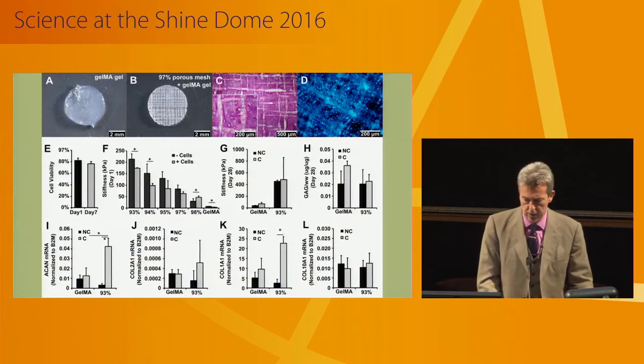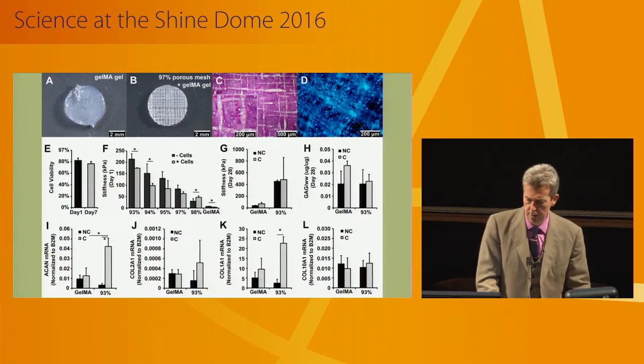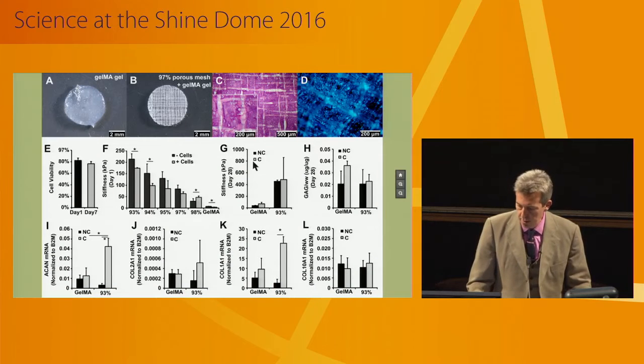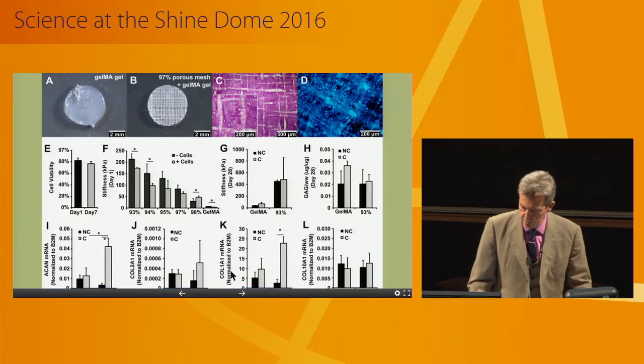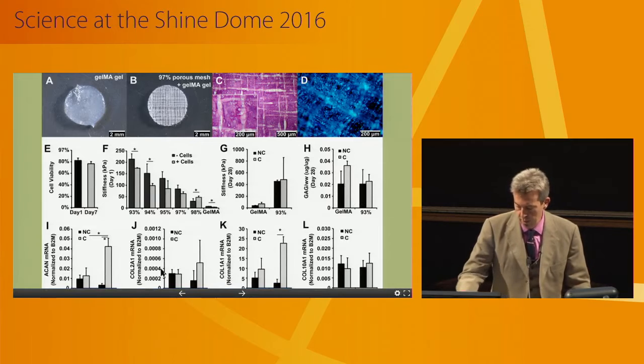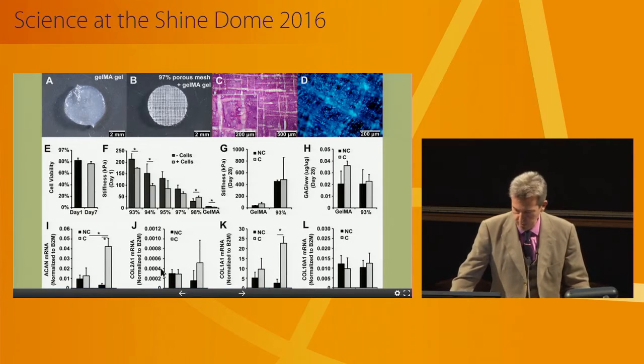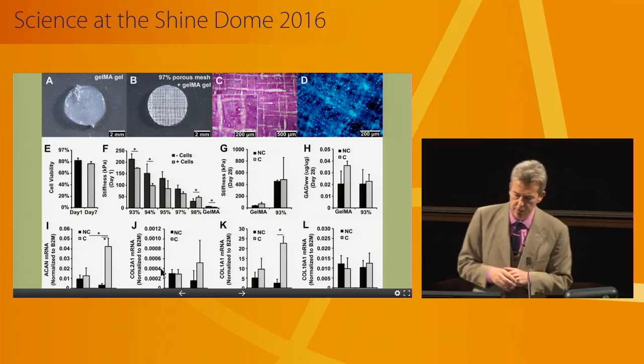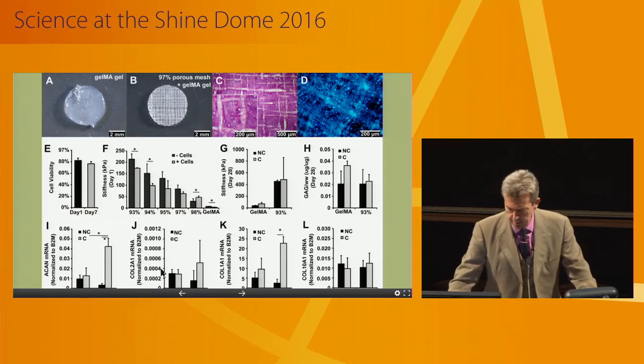But what about the biology? Here you see a long-term culture with human chondrocytes, which are the cells which you will find in the articular cartilage. And you see here that the cells produce very nicely the ECM you would like to see. This is then also shown here in the gene profile, but also on a protein level when we look at collagen 1 versus collagen type 2. Our articular cartilage is mainly made up of collagen type 2, and we get a very strong collagen type 2 formation in the system. So again, this allows us really to direct this biology, and we are now starting large preclinical animal models because the results are very, very promising.